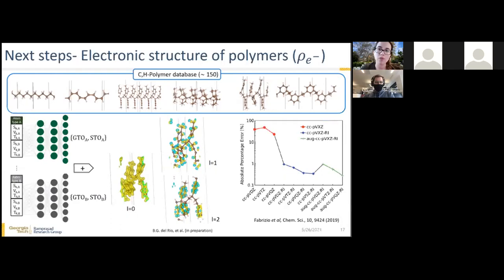So their approach requires an initial decomposition into a specific basis set. And here you can see all the basis sets they try. This is for the case of a water molecule. And they saw that the best performing type of basis sets is the ones called the resolution of identity type, which are used to actually fit the density. Now, these error metrics give the percentage error with respect to the total amount of electrons in your system. And you can see that the decomposition using the resolution of identity gives you around 0.3% error.